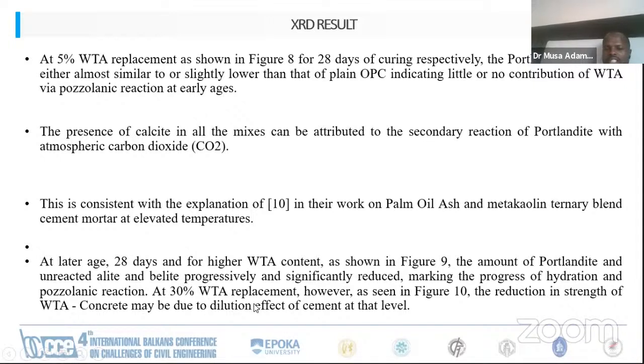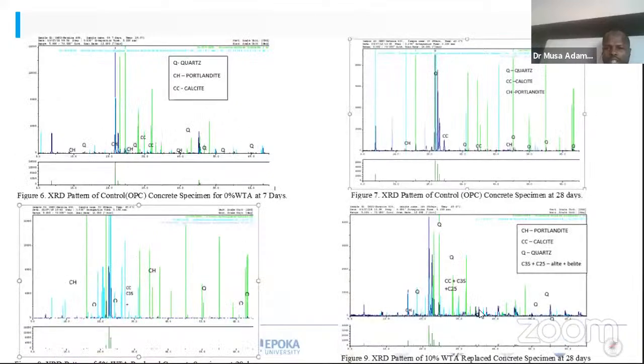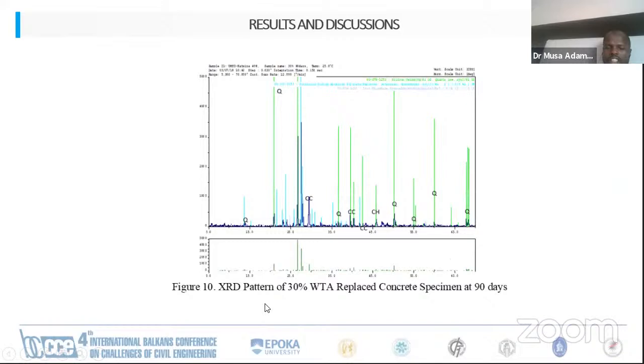At 30% WTA, however, as seen in figure 10, the reduction in strength of WTA concrete may be due to dilution of cement at that level. So these are the figures, as we can see, as explained. And this is figure 10. This is the XRD pattern of 30% WTA replaced concrete at 90 days.